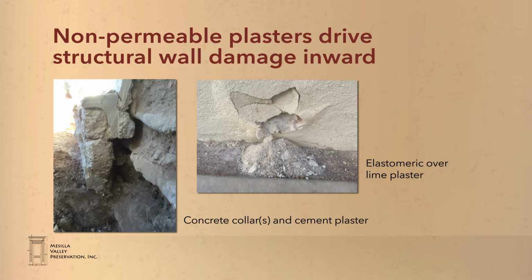Unfortunately, because the concrete is less porous than the adobe, the evaporation has taken place in the more permeable adobe. The moisture simply takes the path of least resistance and evaporates where it has access to air, behind the concrete and behind the cement stucco in this case. The result is that the damage has continued to occur behind the concrete, inside the load-bearing structure of the wall.